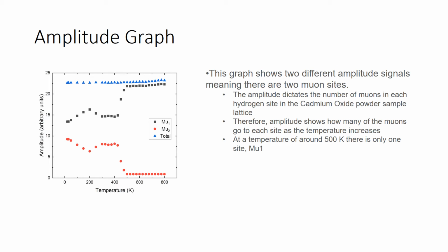When the muons are implanted in the sample, they hit different sensors, which are in the front and the back, which produces asymmetry versus time graphs. These asymmetry versus time graphs can then be fit with different equations to analyze the data and give amplitude versus temperature graphs. And these amplitude versus temperature graphs show different hydrogen sites within the cadmium oxide lattice.